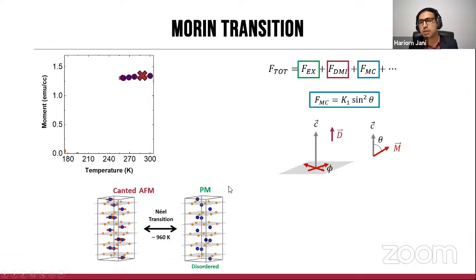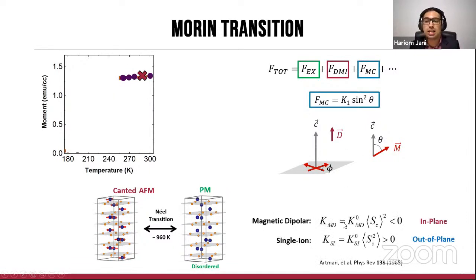The last ingredient is the magnetocrystalline anisotropy, at least the dominant interaction, which is given by an axial interaction emerging from a very delicate competition between magnetic dipolar and single ion. As I mentioned, long-range dipolar fields may still be absent in the system, but local magnetic dipolar interactions enforce some form of anisotropy, which favors in-plane orientation. As expected, this would be the expectation value of the Z component squared for the spin. And then the single ion interaction comes from the very weak spin-orbit coupling in the system. It's weak because Fe2O3 consists of Fe3+ ions, which are almost spherically symmetric, but the deviations from the spherical symmetry allow some spin-orbit coupling, which gives single ion anisotropy favoring the out-of-plane direction.